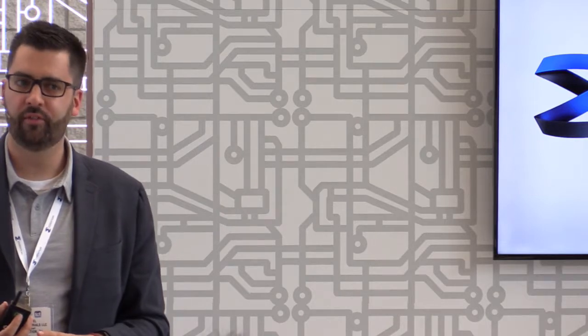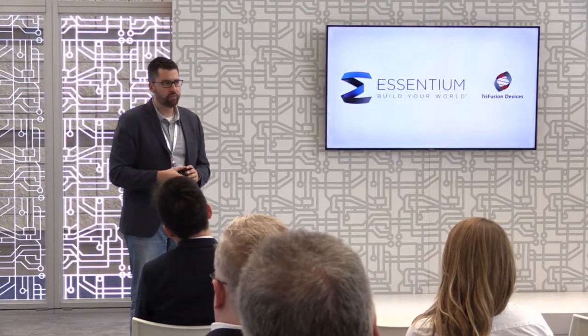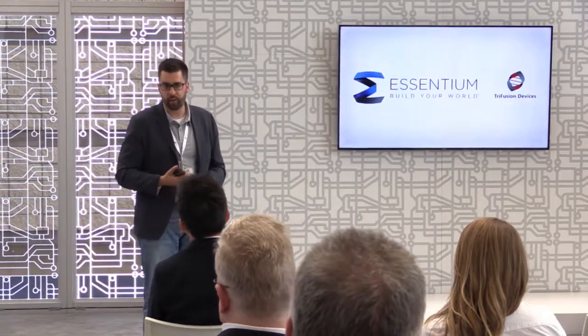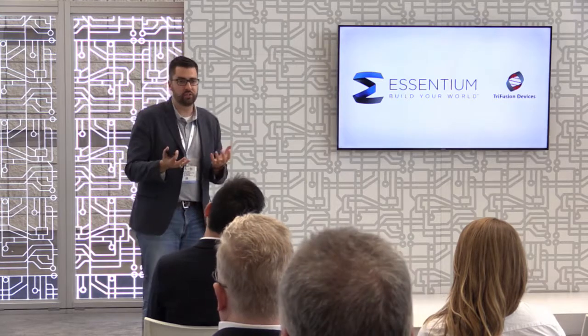They don't burn off. It would take a lot of energy to degrade or create char, any of those things. We make sure that we keep the temperature of the printed part at the critical sintering temperature, below the melting temp, above the Tg, so that we can promote that polymer chain mobility without degrading the polymer, causing shifting or warping of the printed part. It remains dimensionally stable, right?